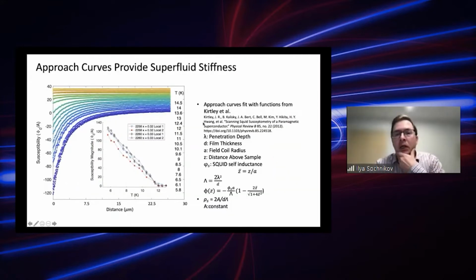Now, the images are uniform, but how do we make quantitative conclusions? To measure the penetration depth, which goes as 1 over the superfluid density, we do what we call approach curves, meaning we move the SQUID close to or away from the sample, and we get this curve, for example, at the lowest temperature, where the signal gets negative, meaning more screening near the sample. Then we can fit these curves to this expression that includes the penetration depth, the distance dependence, and some other constants, and extract the penetration depth itself. This model was introduced by Vladimir Kogan and also John Kirtley about 10 or slightly more years ago.